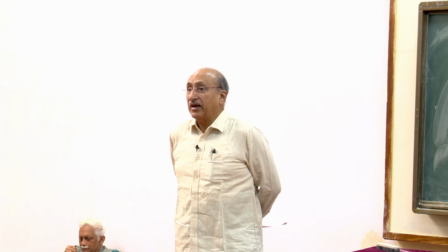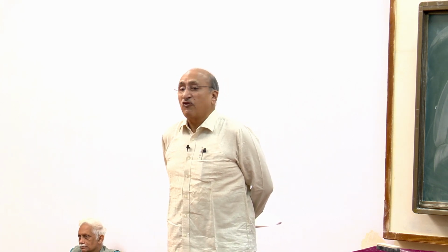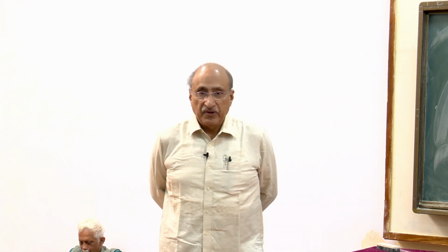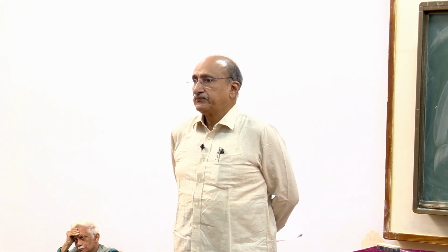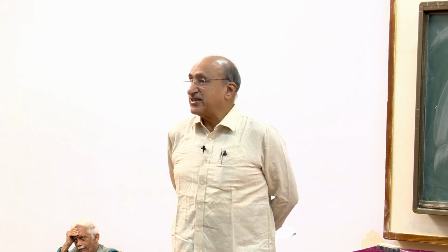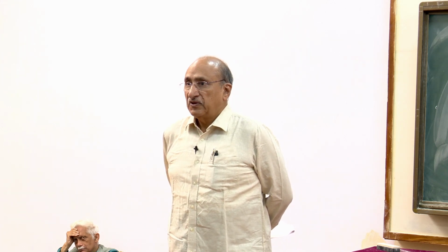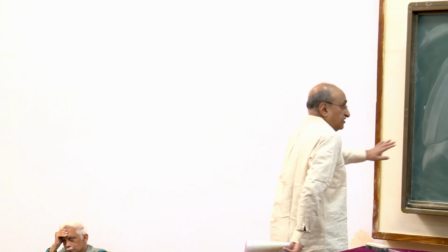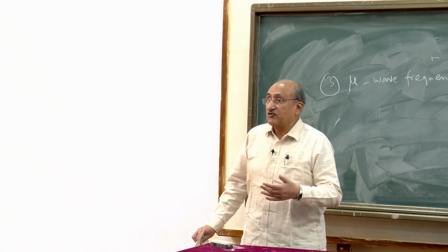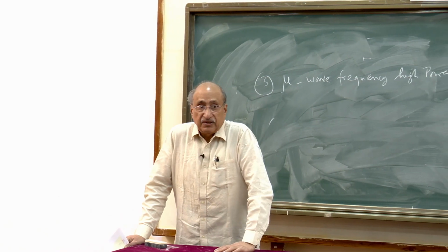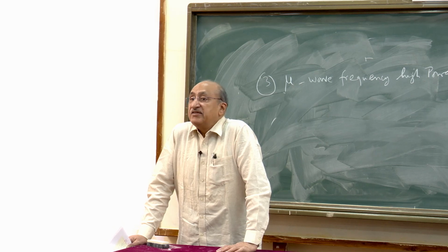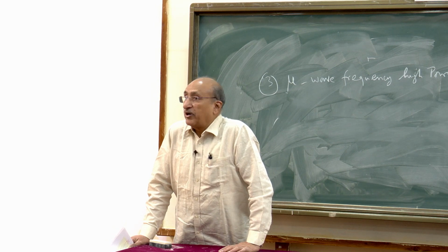Here it's very important that, because of high power, you are always going to heat the material. Magnetic property should not change with heating. And also how the power is dissipated in the system becomes very, very important. So here, not only is high resistivity very important, but there are also many other things which we are not looking for in low power applications, essentially the heating effects. How essentially it changes the properties of the materials upon heating.